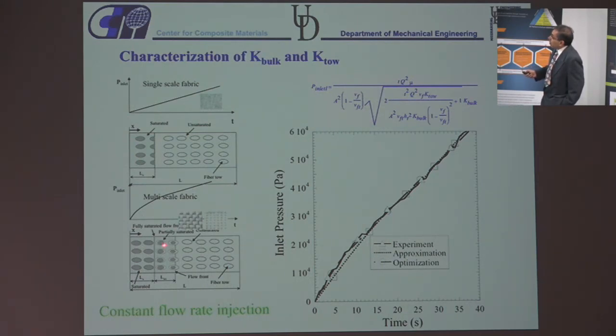If you have tows that are filling a little bit later, the pressure is not a straight line, but it has a little drooping effect, because the resin is still going into the tows while the flow front is here. So when you have a pressure profile at the inlet that looks like this, when you're injecting at a constant flow rate, you can use my analytical solution, which has the bulk permeability and the tow permeability, to match your experimental profile with your inlet pressure here by changing the bulk and the tow permeability.